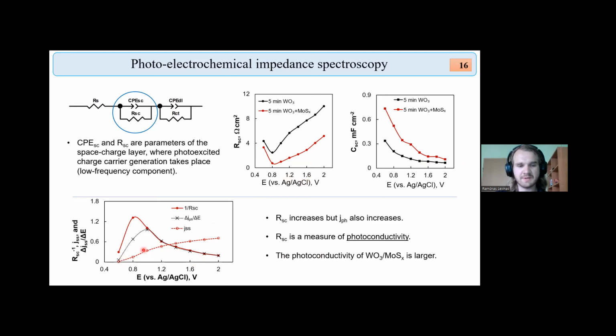And if we examine the steady state photocurrent, which is shown by this dashed line, we notice that with potential it increases. We also saw that in the LSV curves. However, the space charge layer resistance also increases, which is kind of a contradiction. The resistance increases and the current increases. And that is because the photocurrent is proportional to the rate of the occurring photoelectrochemical reaction, whereas the resistance of the space charge layer is instead proportional to the amount of charge carriers that have been generated within the space charge layer, so-called photoconductivity.